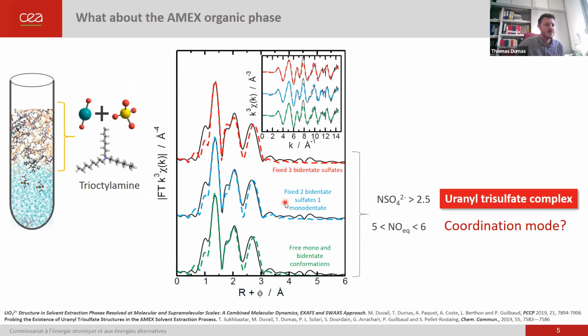So what is going on if you jump to the organic phase in trioctylamine? And here is what you measure if you do that. So this is our result that we measured at the Mars beamline. And on this spectra, the black one are the experimental spectra, right after measurement, you see that you have a huge peak that arises in the second coordination sphere of uranyl. And this is related to an increase of the amount of sulfate in the uranyl coordination sphere. And if you try to fit it with different models, you always have to add free sulfate in this fit. Okay, but you also have to manage if the sulfates are bidentate or monodentate, and from this data, it is not easy to determine whether it is one way or the other.